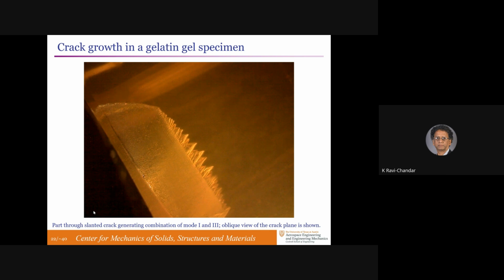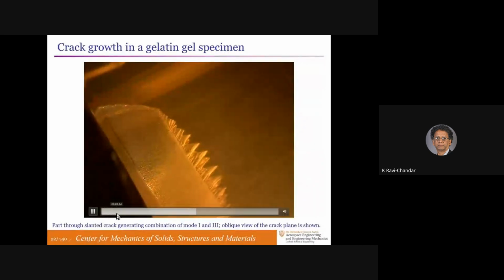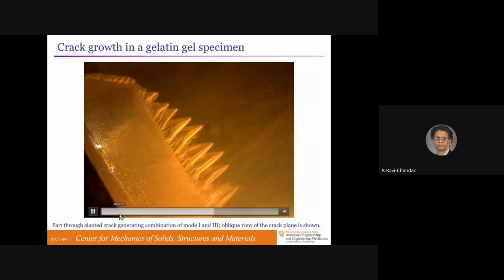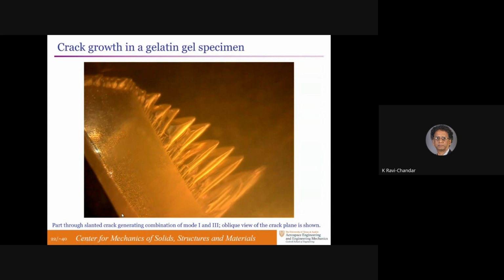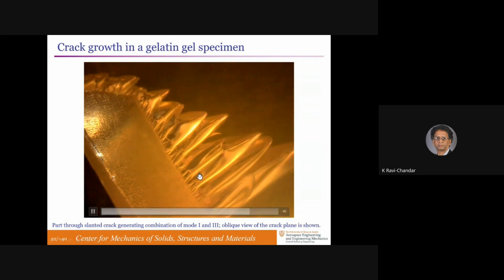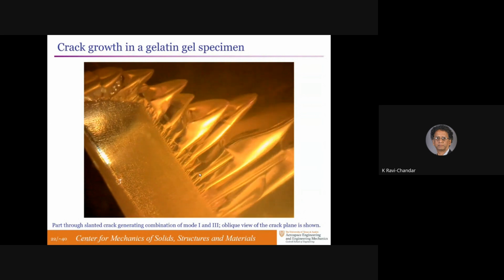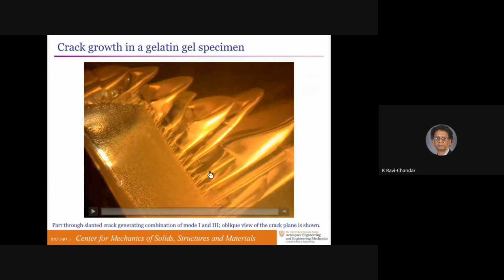So the crack is at a slant to the geometry of the loading, but we're looking at it as a projection. So you could see the daughter cracks starting to grow. And if you pay attention to some of them, they'll fall off. The other ones keep going. We play it again.